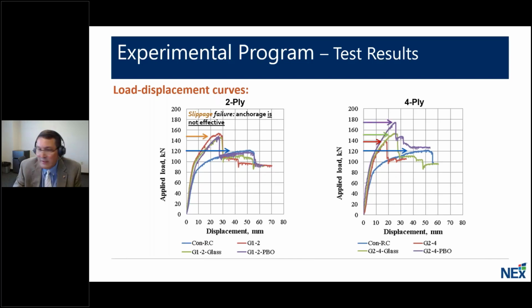And then finally, when we go to using the PBO system developed at Missouri S&T, we see the greatest increase in capacity. So again, the takeaway here is, when we have the debonding failure, any type of these anchored systems is effective to delay a premature debonding failure, give us better ductility, and give us additional capacity. So just remember, fiber slippage, 1 and 2 plies in our work, and above that was a debonding failure.